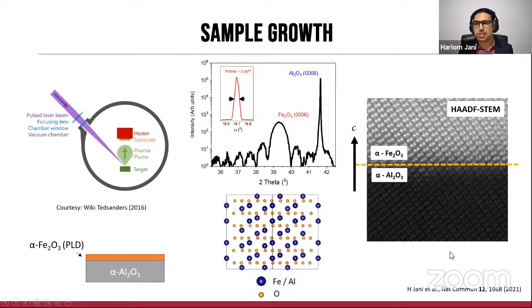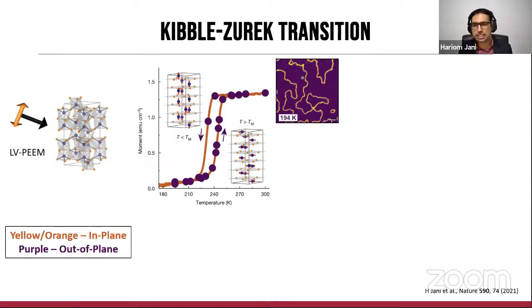Now, having all this established, let's actually look at the experimental data, where we now have the Morin transition, which I have sort of convinced you about, and we start from the low temperature state, and we're looking at linear vertically polarized imaging. And if we look at this image here, we see predominantly it is covered in purple because we are in the low temperature easy axis phase, and therefore purple color corresponds to out of plane orientation. And then there are these walls separating various domains, and evidently these are going to be the antiferromagnetic domain walls in the sample, which are then colored yellow-orange.